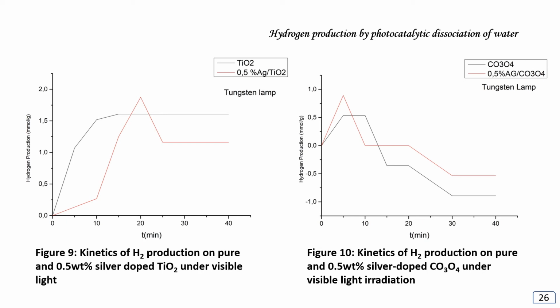Note that for pure and doped Co3O4, the amount of hydrogen produced beyond 20 minutes is negative, which could be explained by the fact that the production of hydrogen by photolysis of Na2SO3 becomes preponderant compared to that obtained by photocatalysis. It is important to note that whatever the oxide used, the silver doping exalts the photoactivity of the oxides. It is interesting to note that pure Co3O4 is active under light radiation.